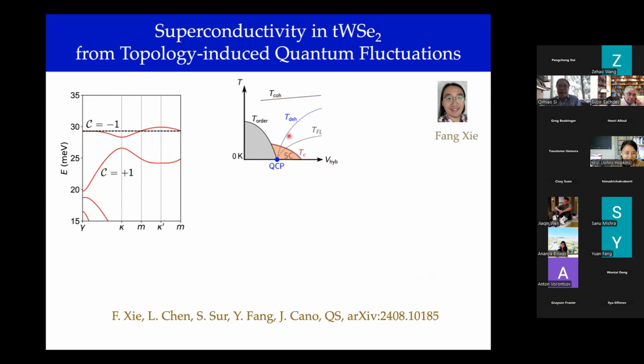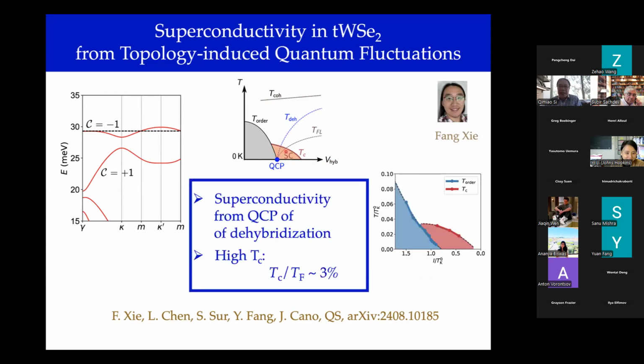And there's various kinds of scales which are borrowed from the heavy fermion experience, and realize a quantum critical regime that drives superconductivity. And we did numerical calculations to show that in the vicinity of electronic order, which is the analog of this curve, this cartoon curve, these are actually numerical data, and to show that there's a superconductivity, and TC is a few percent of the effective Fermi temperature as specified by the low energy physics, very much in the same spirit as how these scales are considered in the experiment, as I mentioned.